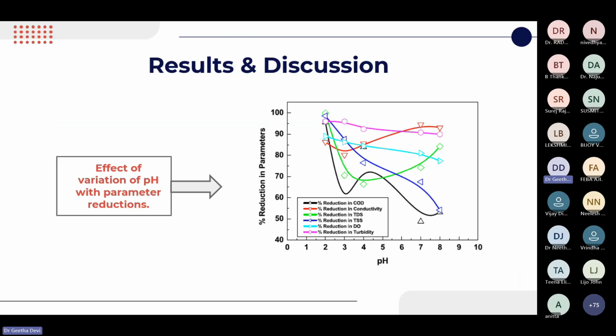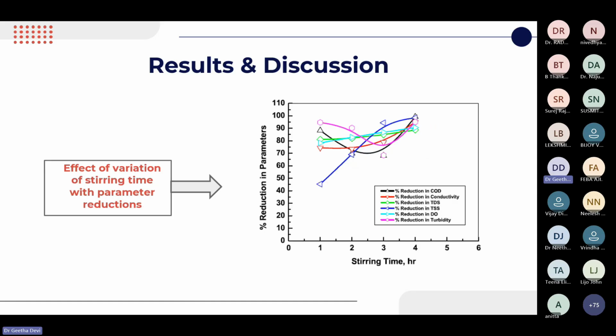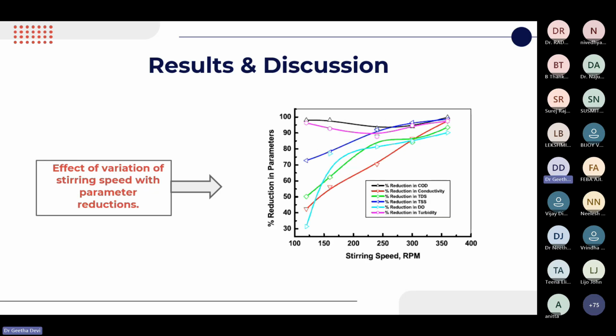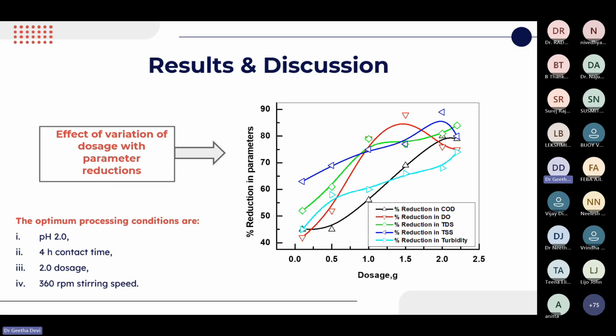And this is the experimental outcome when we increase the pH from acidic to alkaline range. These are the results we obtained. And also the stirring time was varied. This is the result for stirring speed and also the dosage of nanoparticles, and the optimization of these parameters has been done, and the optimum processing conditions obtained were pH 2, 4 hours of contact time, 2 gram per liter of dosage and 360 rpm stirring speed.